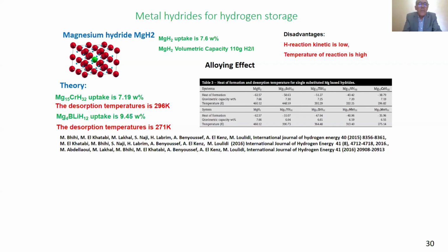And this has been done using density functional theory, and it has been shown that by substituting magnesium with another element like chromium, for example, the gravimetry is still high, but the desorption temperature is around room temperature. We can even improve the gravimetry by substitution with light elements like beryllium or lithium. In this case, we can increase the gravimetry and at the same time reduce the desorption temperature.